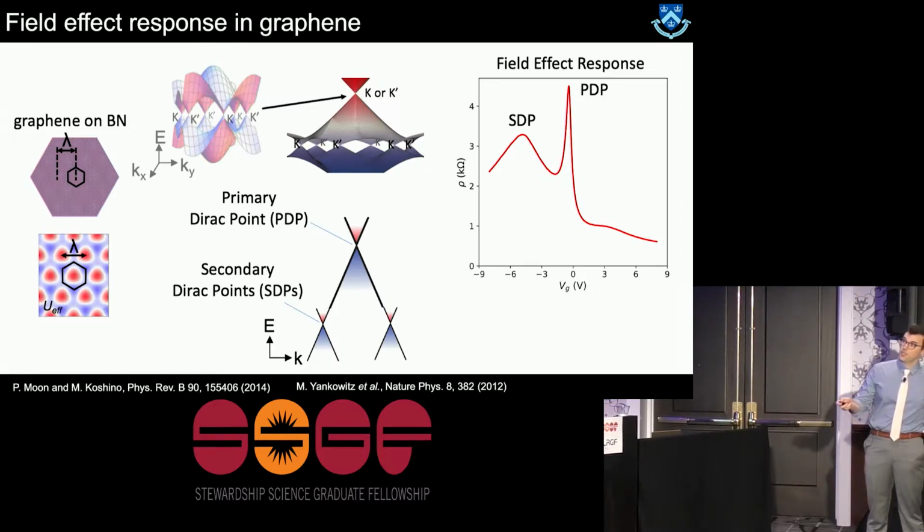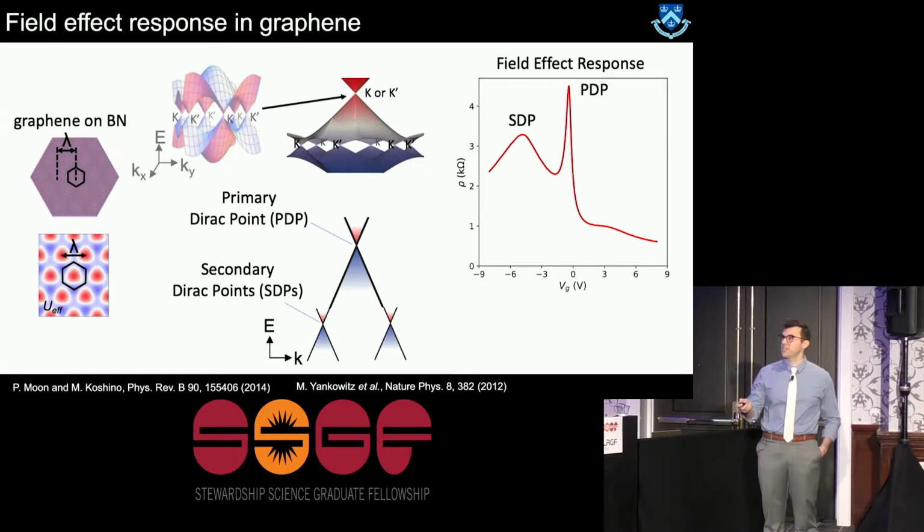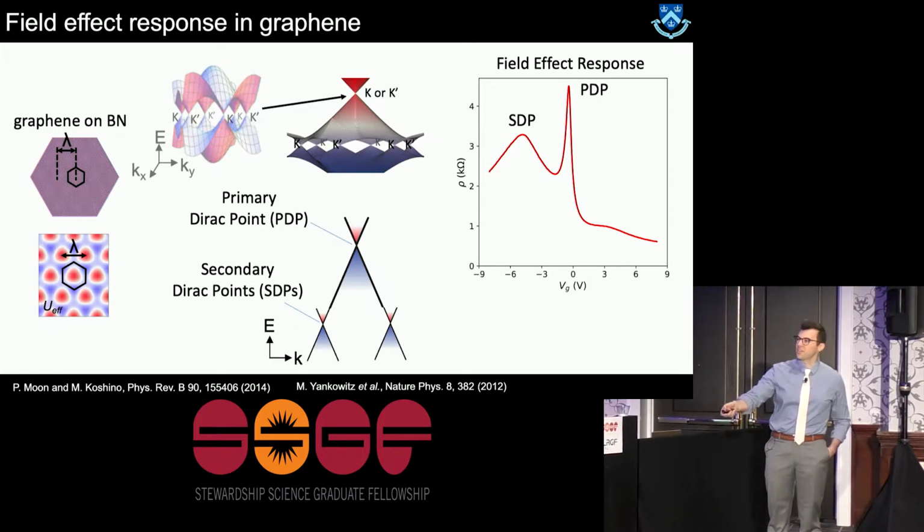The graphene band structure evolves to have these replica Dirac points, which is due to zone folding, shown here in this schematic. I'm covering the laser, that's why. Shown here in the schematic is that I get these replica secondary Dirac points. I'm going to label these primary and secondary now. And if I sweep my energy by changing the gate again, I'm going to sample the original Dirac point, which I can see here, but I'm also going to sample these new points.